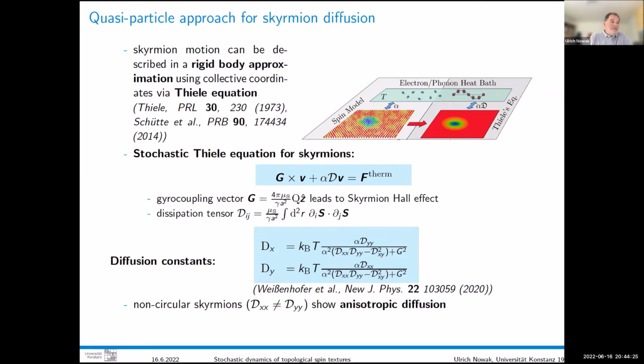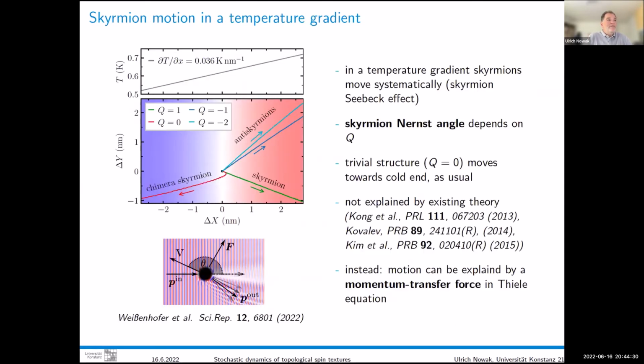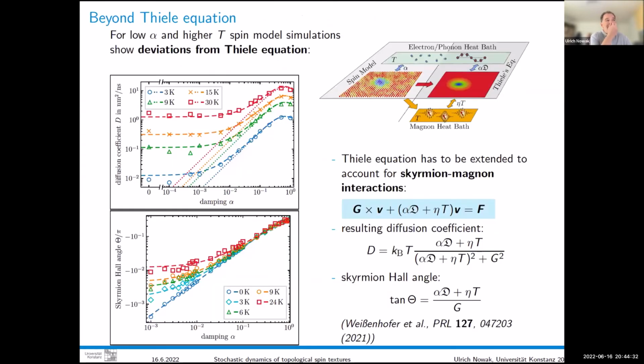But it's even more interesting. There's also this fact that I showed before, that there are some slight deviations from the analytical solution of the Thiele equation. And if we looked into this more carefully, by going to lower and lower values of the damping coefficient alpha. So in the first graphs, we went down to 10 to the -2, and that looked pretty good compared to the simple theory. But if you go towards 10 to the -3 or 4, you see there are big deviations.